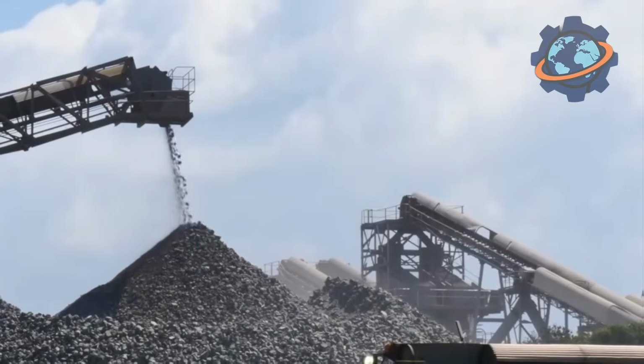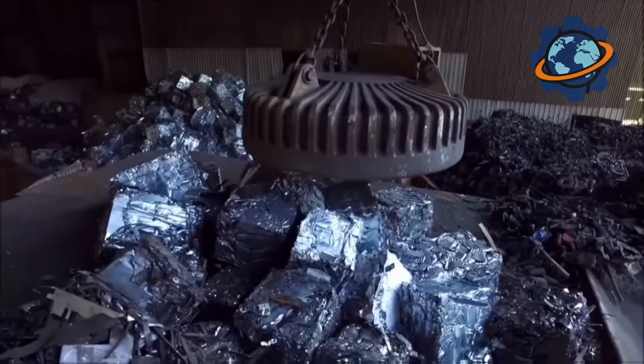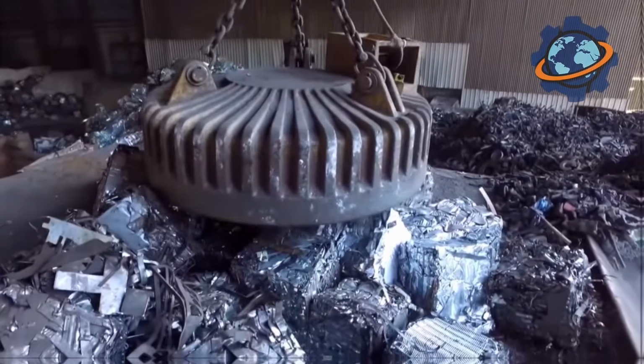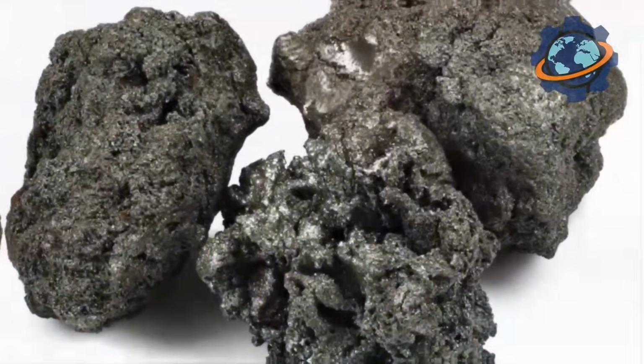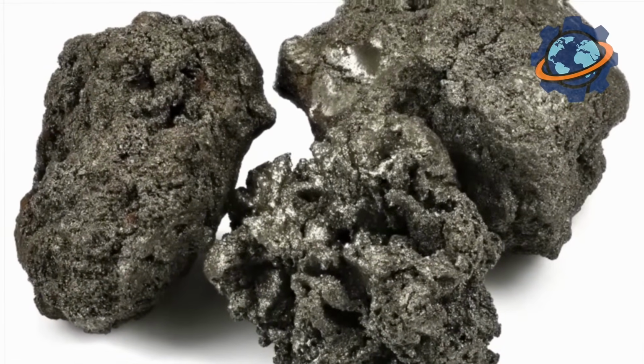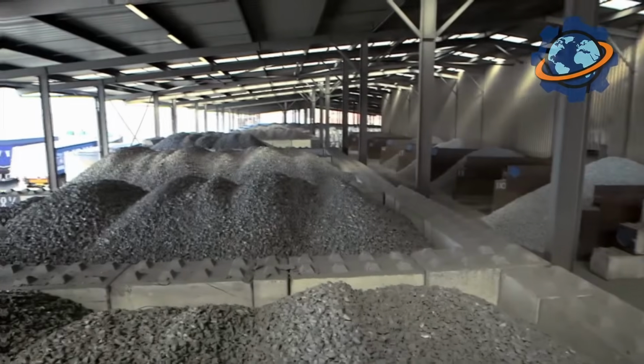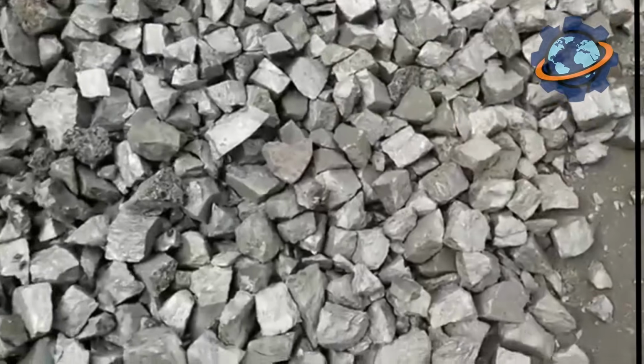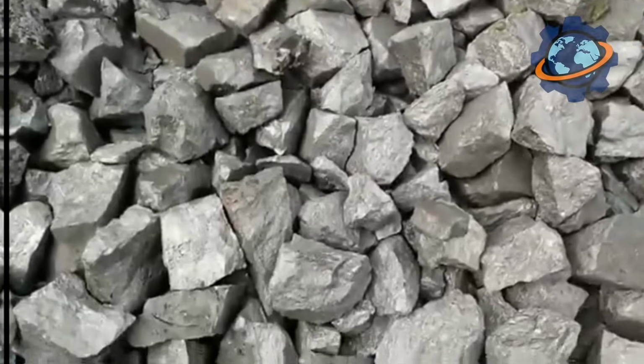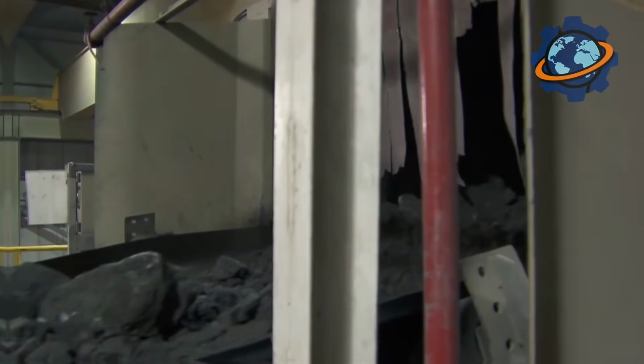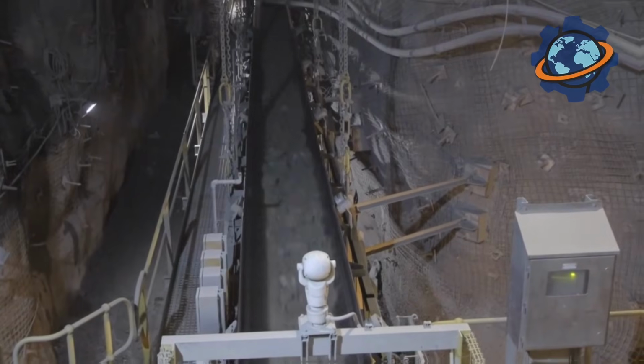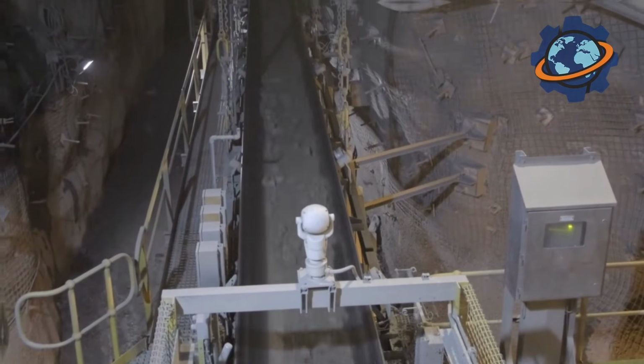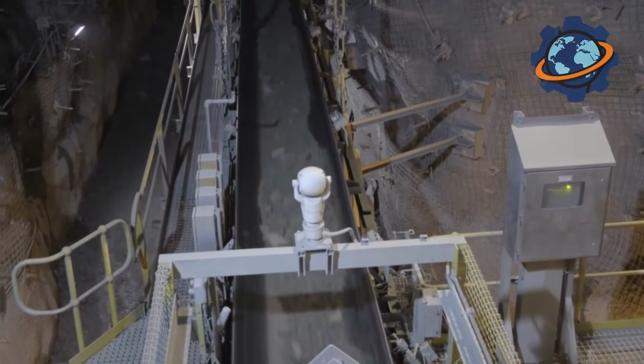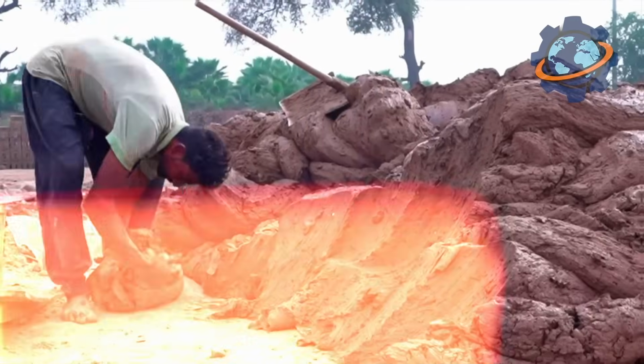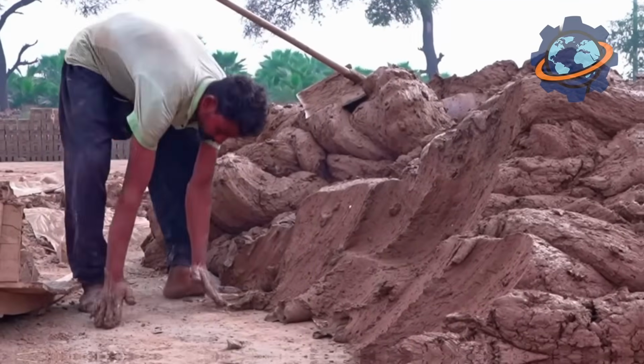So, the process begins with the preparation of components. The mined clay and other rocks, as well as the pre-prepared chamot, are sent to the crushing line. Giant crusher jaws break large pieces, and then roller and ball mills relentlessly grind them into a fine powder with a clearly defined grain size. Control of the fractional composition is extremely important because the future density, and consequently, the strength and thermal conductivity of the brick depend on how tightly particles of different sizes can pack together.